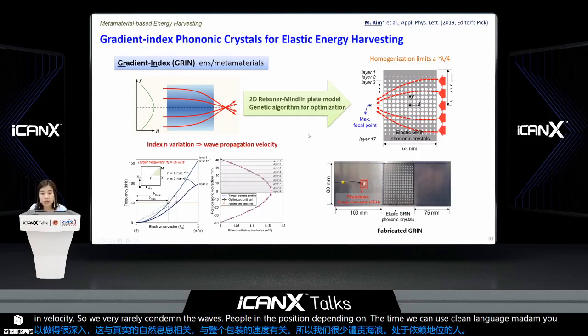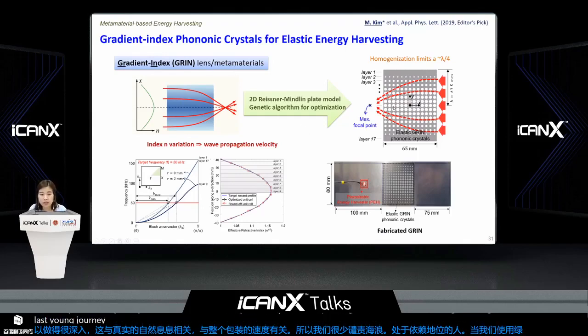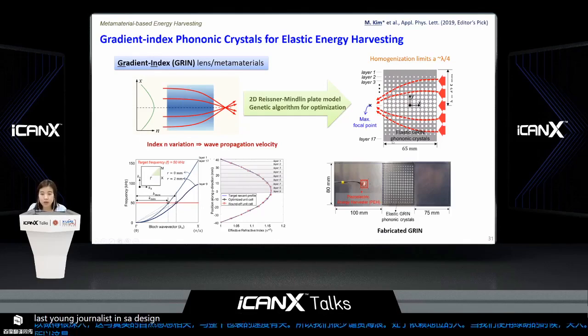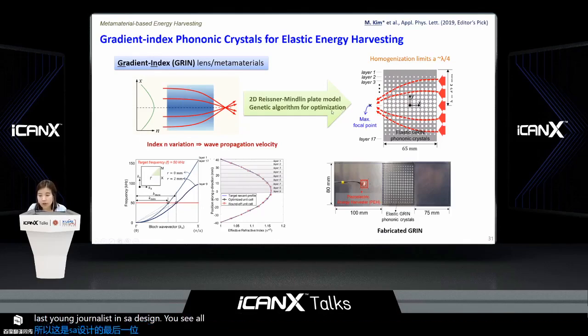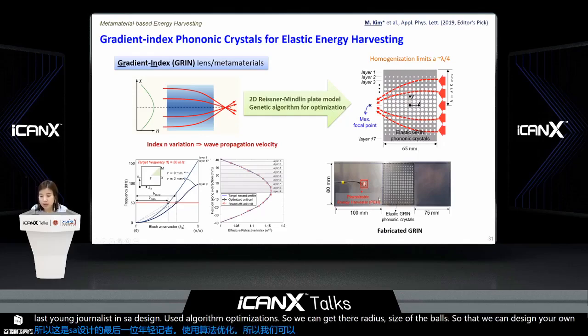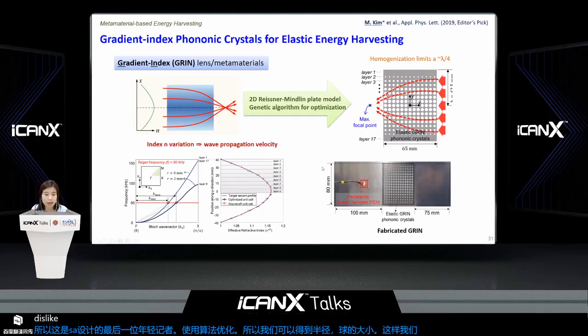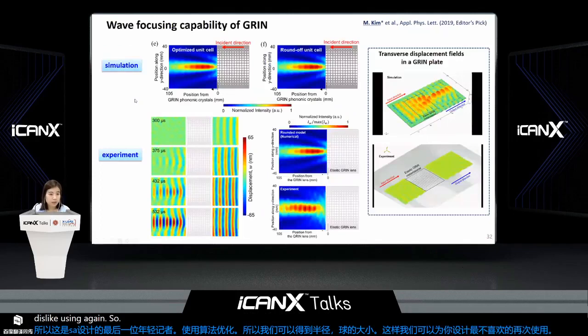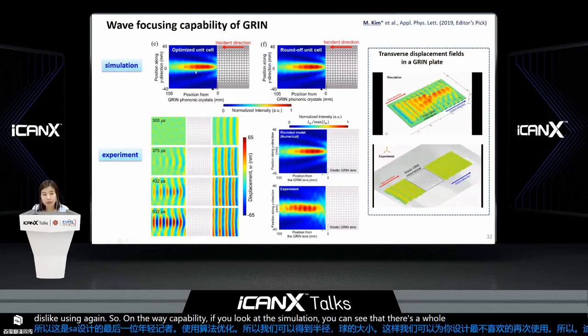So this is elastic energy harvesting. We used a genetic algorithm for optimization so that we can get the radius size of the holes, so that we can design the whole elastic GRIN lens like here, and we fabricated it using an aluminum plate again. We looked at the wave focusing capability first. If you look at the simulation, you can see that there's a focal point here and then a focal area that is a little bit distributed.